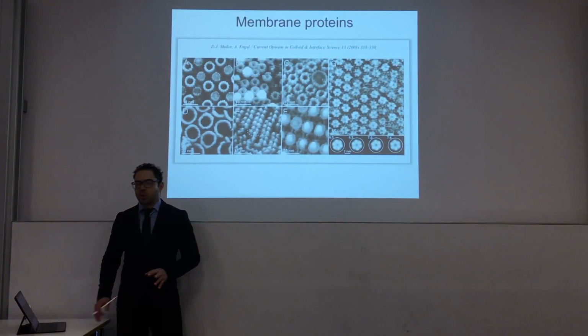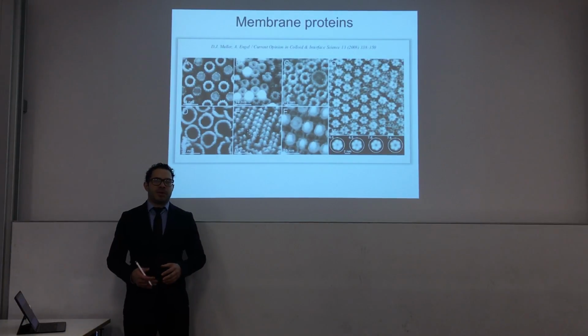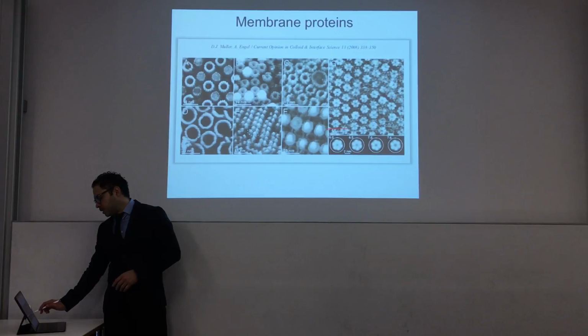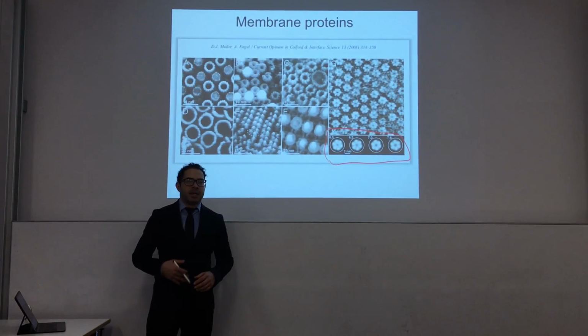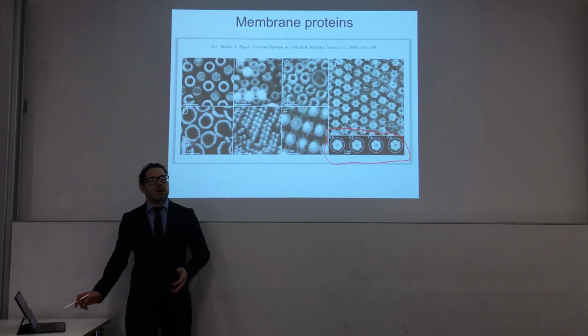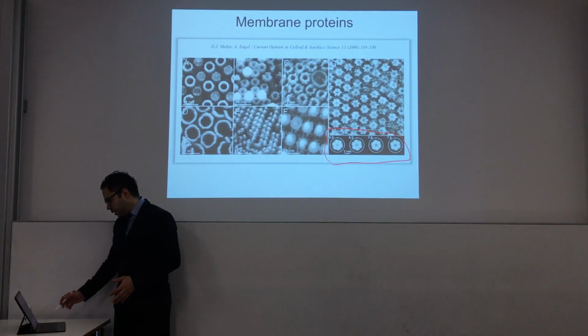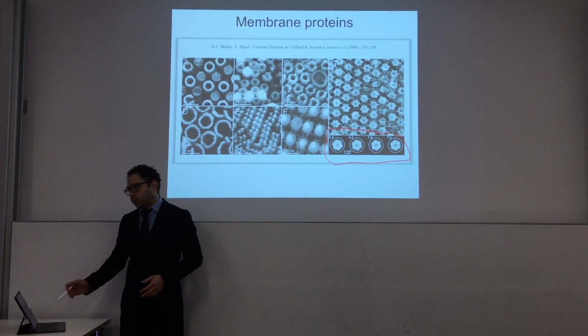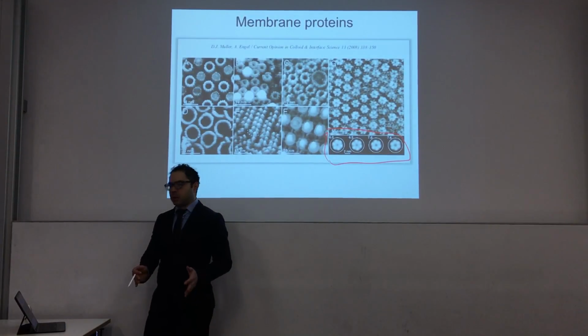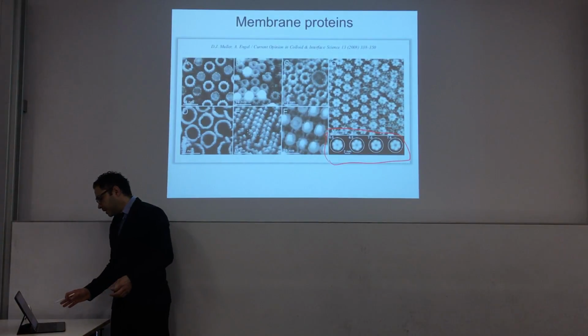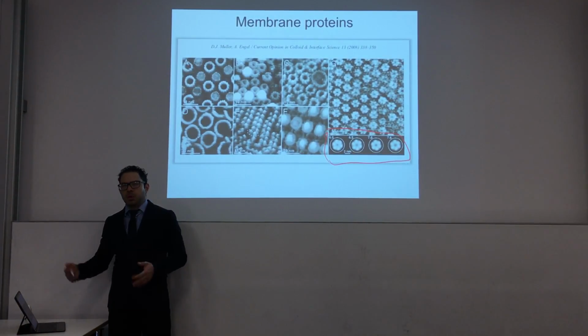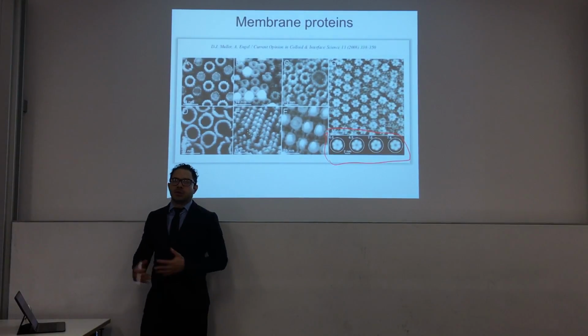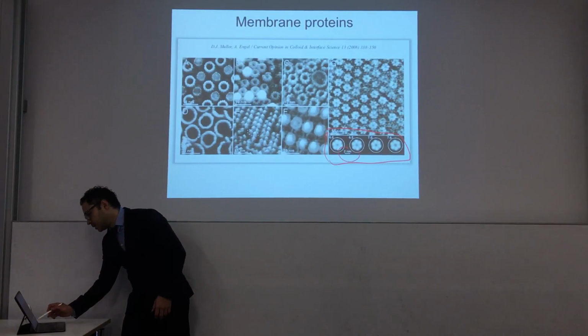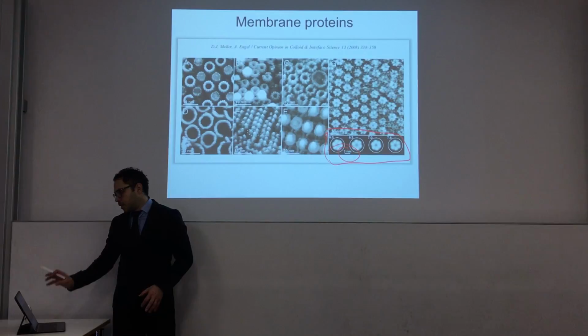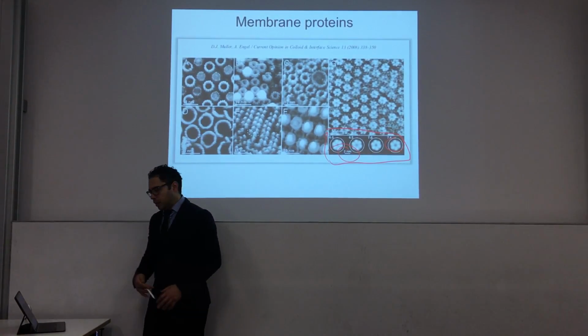Contact mode AFM, in this particular case, when you operate it in liquid, can give very good results. What you see here is an atomic force microscopy image of different membrane proteins, and you can even see, like in this panel here, the possibility to visualize them live in operation. What you see is the opening and closing of ion channels of a membrane in reaction to different pH, for example, of the system. At pH 6 the pore is more or less closed, and you increase it to pH 7.6, and then this pore opens. So this is a beautiful application of how atomic force microscopy allows you to visualize such systems with incredible resolution. You can see the scale bar here is 2 nanometers, and each of these units is a single membrane protein.